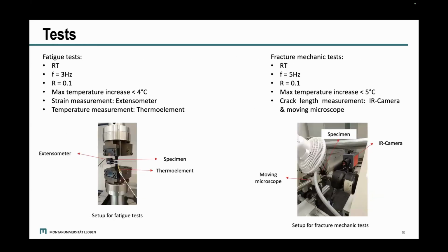Then we have an overview on the testing setup and also testing condition. For the fatigue test, we performed the test at room temperature, and the testing frequency was 3 Hertz under a stress ratio of 0.1. And we measured during the test the temperature changes in the specimen to be sure that we do not have any critical temperature increase in the specimen, because we know for polymers, if we have even a small temperature increase, we would have remarkable changes in the mechanical properties of the material.